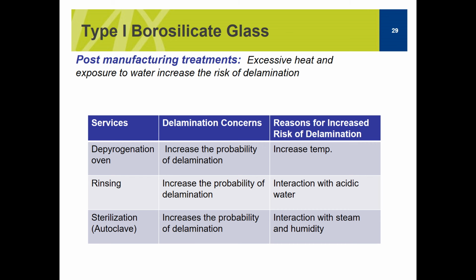Okay, so depyrogenation increases the risk of delamination. Why? Because of the high temperature. Rinsing, the same thing, it increases the risk of delamination. Why? Because of the interaction of water with the glass. And sterilization would be the same thing, especially if we talk about autoclave where we have steam. So right now you have both high temperature and also water. And again, any interaction with water or heat is going to have a negative effect on the vial, as it increases the risk of delamination.